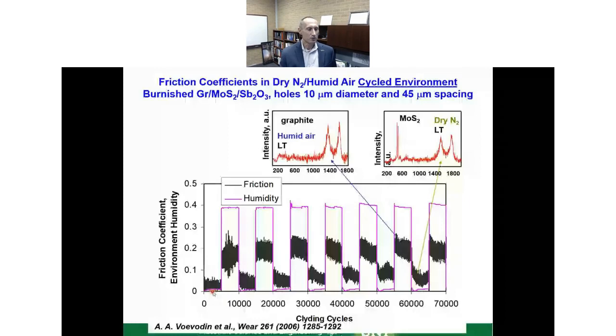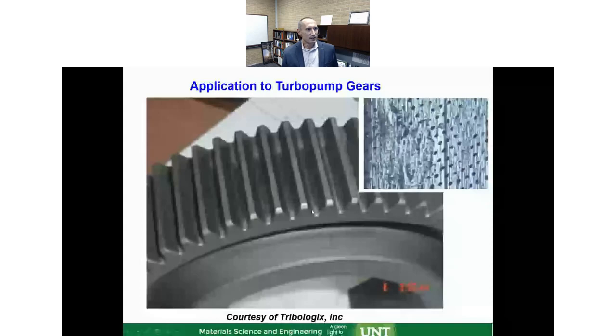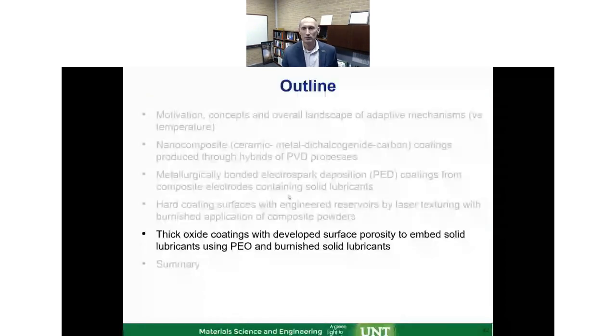To confirm that this goes back and forth, we have cyclic humidity tests, where the humidity goes high, goes low, and friction recovers every time, with lubrication by molybdenum disulfide in dry conditions, or lubrication by graphite in moist conditions. And we are confirming with Raman techniques that the actual adaptation has occurred. So it's working very nicely. And then my industry partners, and this is an example from Tribologix, applied it. This is a gear, which is intended to work in low temperature cryogenic conditions. You can see the dimpled surfaces on the gear surfaces and the coverage here, and that is working very nicely for turbo pumps.